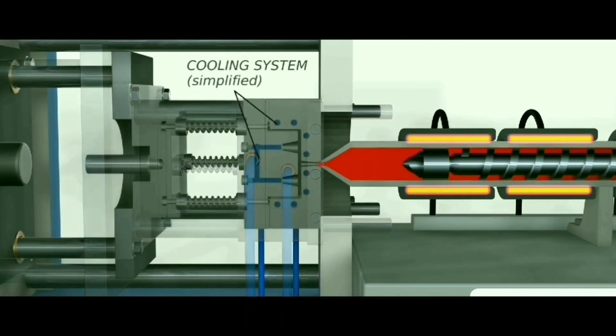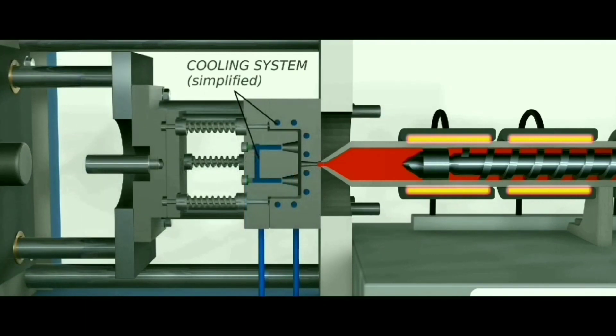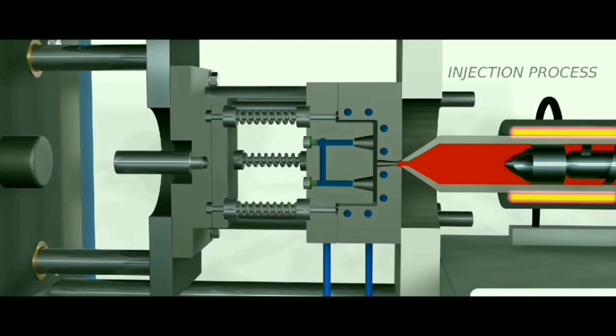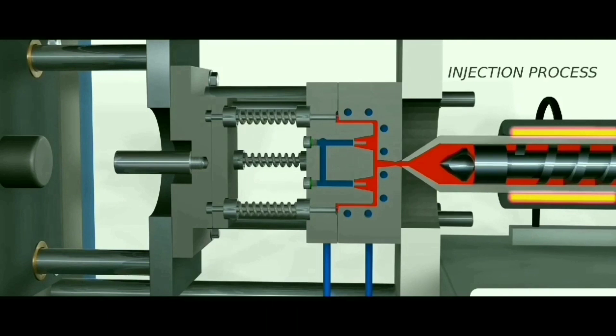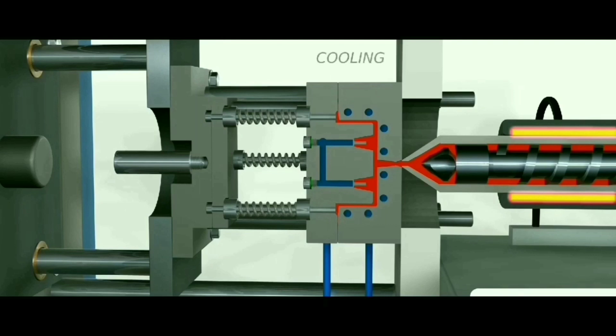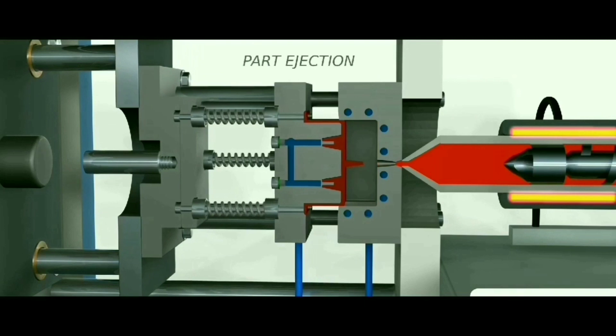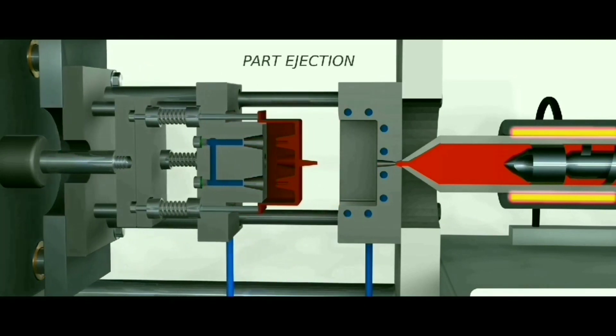We cool the mold using either an MTC (mold temperature controller) or a water cooling tower system. Now we inject the plasticized raw material accumulated inside the barrel into the mold — the reciprocating screw moves forward and the material accumulated over the tip of the screw is injected inside the mold under high pressure. This is the most common and efficient machine used in plastic injection molding industries. After injection the screw moves backward and dosing starts — meaning charging of material from the hopper through the barrel to plasticize for the next shot.